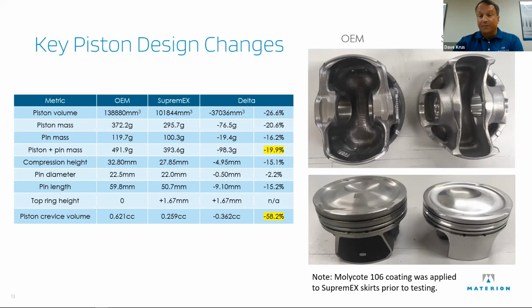And the other thing is the crevice volume was a 60% reduction. So getting that ring that much higher, that's a desirable thing to do for any engine. That brings the top ring closer to the crown to allow heat to get out. Not having the cast iron ring groove insert allows you to be conducting basically through aluminum, so it's much more conductive than the cast iron. And just to note that the aluminum groove was not anodized. It wasn't protected at all. This is just machined Supreme X.